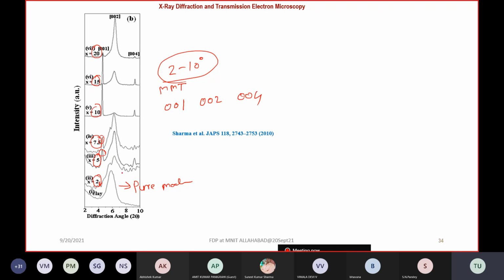If I say that this peak has shifted to this side, you may not believe it. But when you see that this is the 004 peak, this is the 003 peak, this is the 002 peak, and this is the 001 peak, then you believe that all 4 peaks are available. Otherwise you would say this is the 002 peak, but the 002 peak already comes from the higher angle side. As you know, 2d sin theta equals lambda, so sin theta equals lambda upon 2d. D and theta have an inverse relationship. If theta decreases, it means the d spacing increases. So here the d spacing is increased.